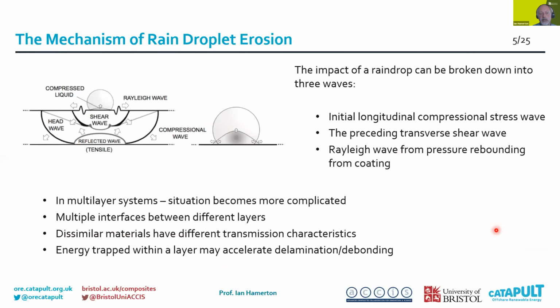It sounds a small thing, but rain droplet erosion is potentially a big problem because of the repeated high-speed impacts. And you can see in the schematic on the left-hand side here, the impact on a surface of the blade essentially evokes several wave responses. Initially, a longitudinal compressional stress wave, preceding a transverse shear wave, and then a Rayleigh wave at the surface,